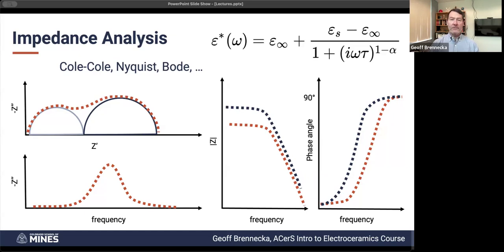You can do the same sort of plot as a function of frequency, and you can see that as you increase frequency, the impedance is dropping here. And that's because one of your polarization mechanisms just can't keep up. So that might be the mobility of your charge carriers, if you have conducting electrons that are low enough in mobility that they can't respond really fast, or maybe you're at the point where you're stretching the ions between lead and oxygen, and you're wiggling fast enough that the high mass lead just can't keep up.